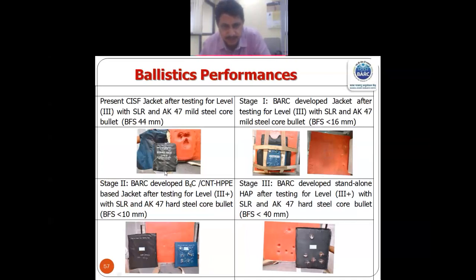The first is the result with existing jackets which we took from CISF, previously existing jackets. This is the trauma, meaning after we fire the bullet, you can see that the depth is high. The similar specification Bhabha Kavach has almost nil trauma, very low, less than 16 mm. Here it was 44. So when we developed level 3 plus, the backface signature was less than 10. Here you can see.